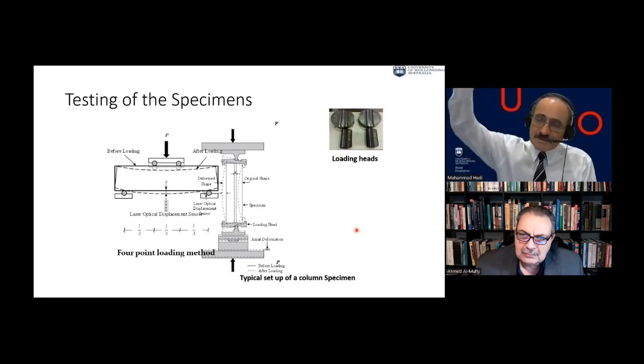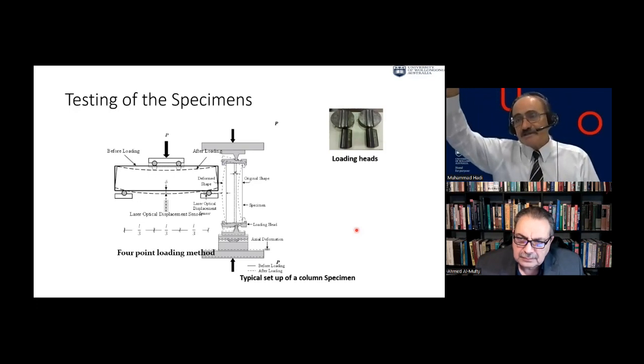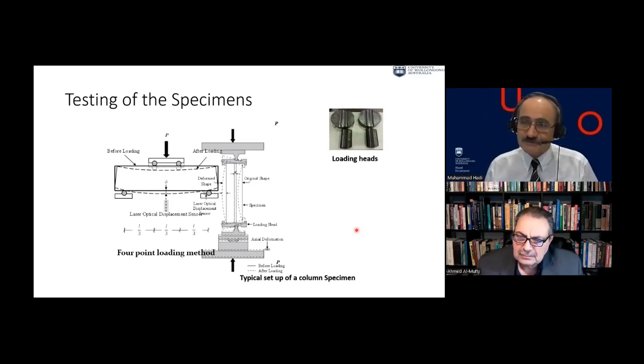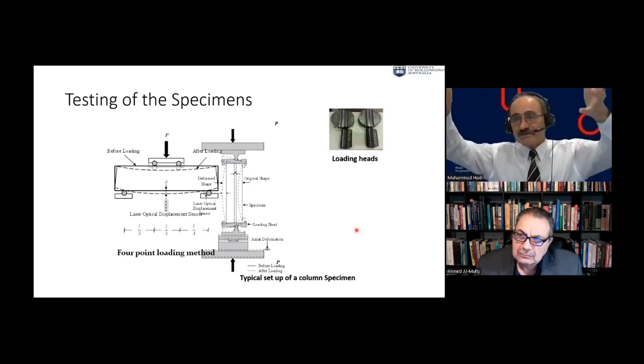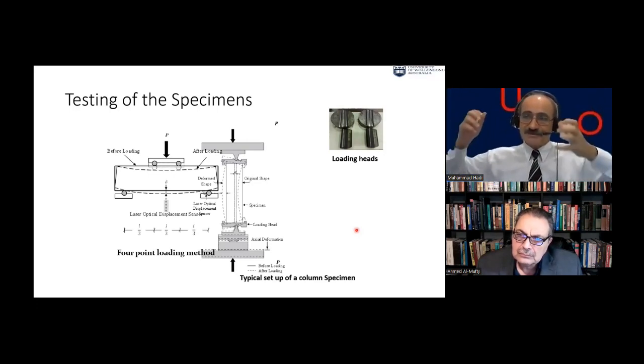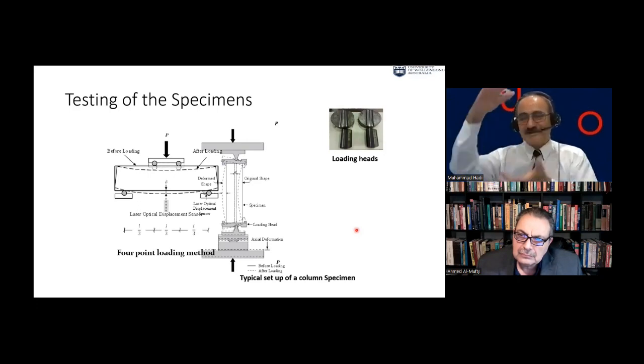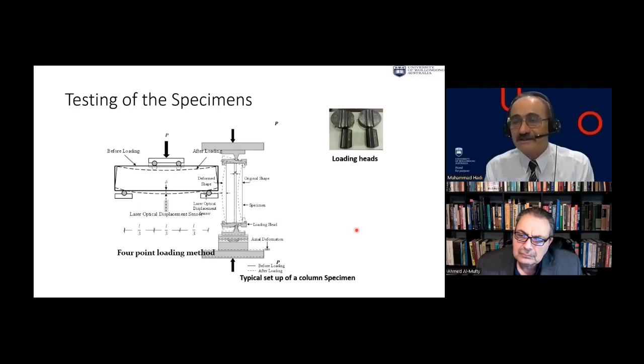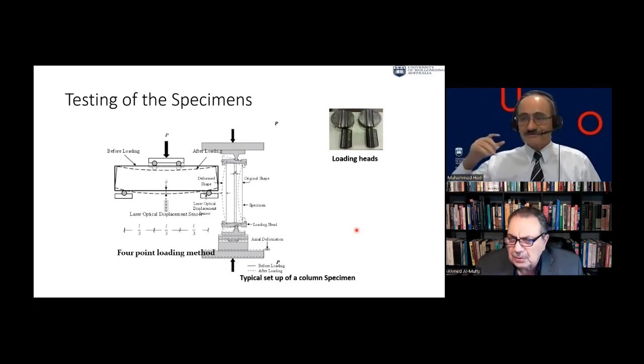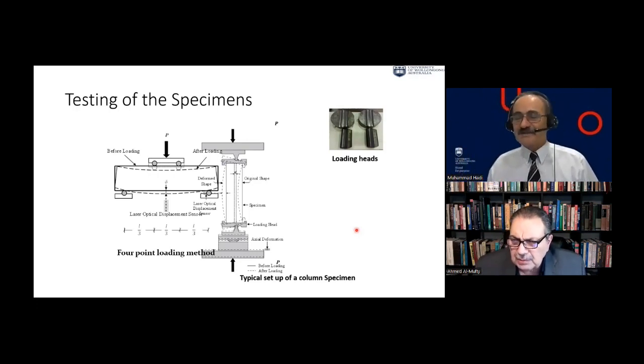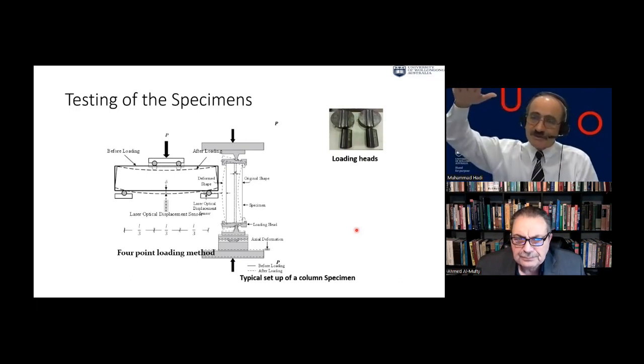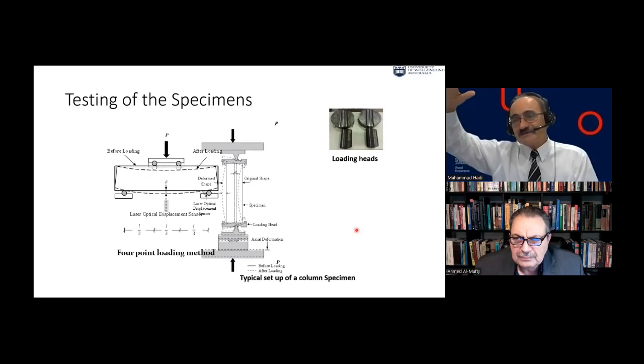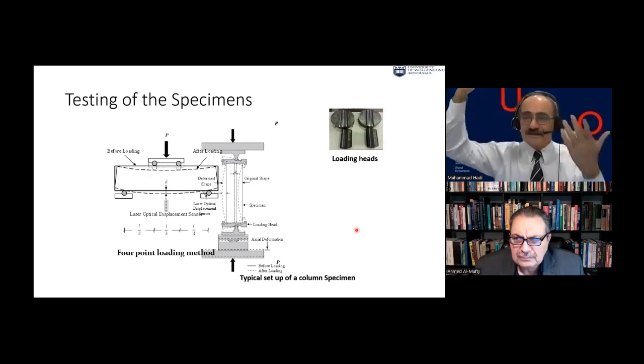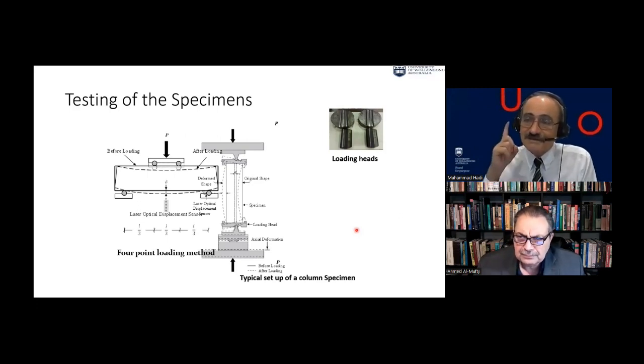But for the big specimens, every specimen takes 2 to 3 hours of testing. I don't want to bore you. They are all displacement controlled. And then placing those specimens, they are 200-300 kilograms. So a forklift brings it, makes it square, and they start the testing, force controlled. Of course, it's difficult to hold them by hand. You need a machine, because 800. And then you need to cap them with a high strength plaster and leave it in the machine to set, and then you start testing. So it takes 3 to 4 hours for each specimen.